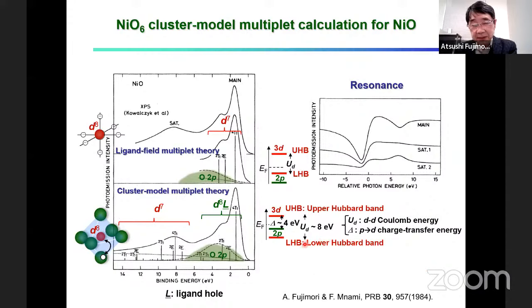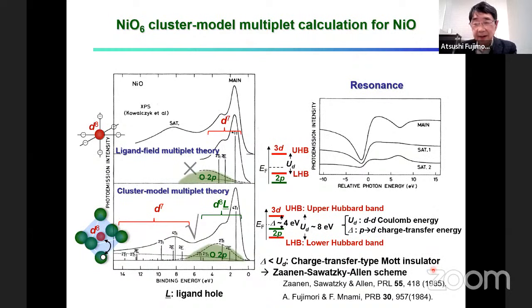The parameter value U is quite large, Coulomb energies of the order of 10 eV, and the charge transfer energy between oxygen P and D is several electron volts. So this is classified as a charge transfer type Mott insulator.